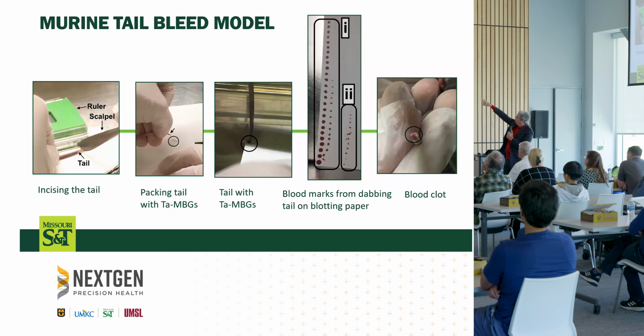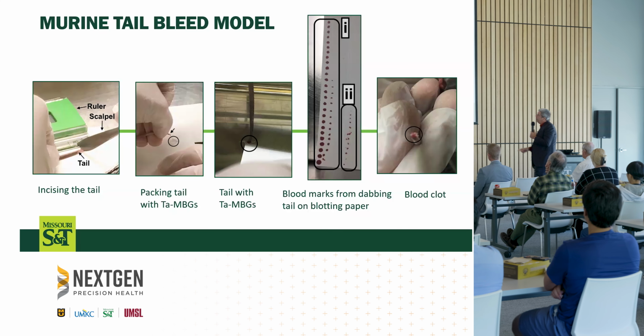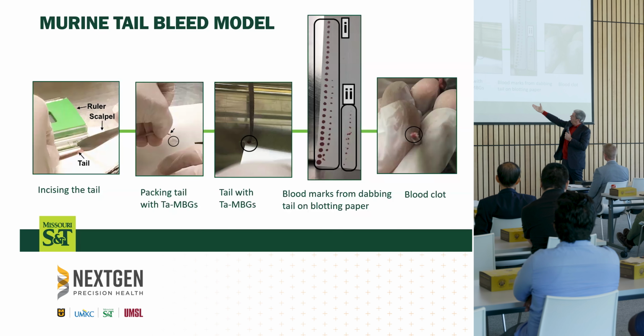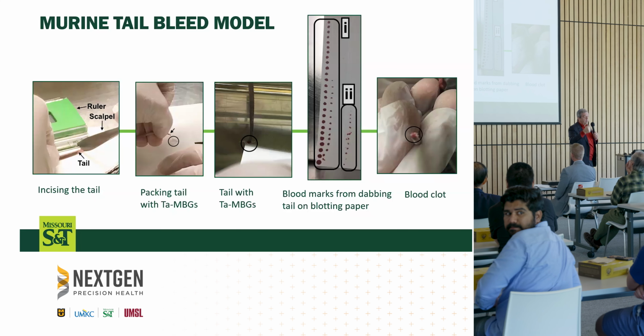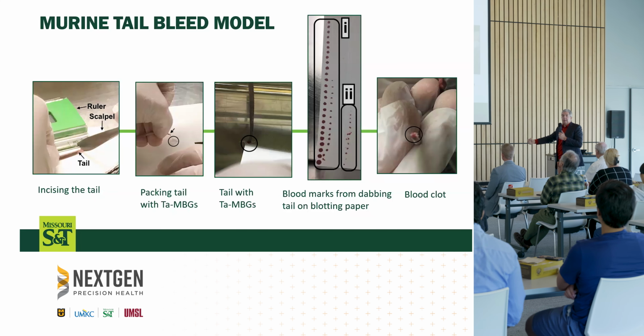Those dots on there are about 15 seconds apart, I think. So it takes 2 or 3 minutes for the mouse to clot, but they will clot naturally. The way to evaluate whether our material is able to accelerate the clot, to reduce the bleeding time, is to take a thin layer of the material you see here, put it onto the end of the tail, post the cut, and pick up the mouse again and go along and dab it until it stops bleeding.